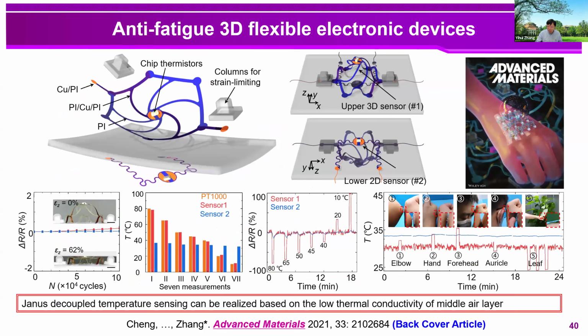Based on this strategy, we have developed an anti-fatigue temperature device capable of decoupled temperature sensing based on the low thermal conductivity of the air. As you can see here, one of the sensors is on the back of the substrate, and the other is on the top of the 3D structure. So by using this kind of device, it can monitor the temperature of the contacting object and the temperature of the sensor itself. And this device can be compressed repetitively to around 62% by over 100,000 times without failure.